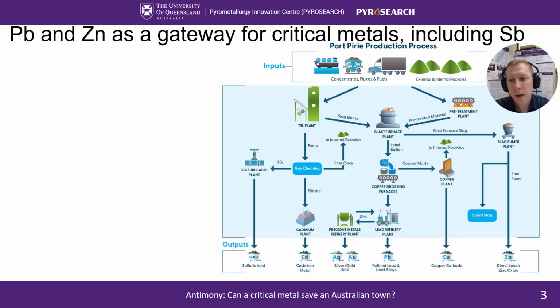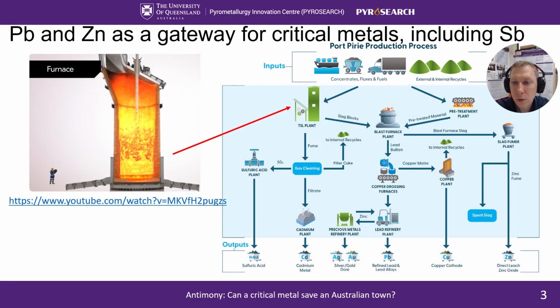This is a simplified flowsheet of the lead and zinc process. The raw feed arrives on ships, trains, and trucks. It consists of concentrates from lead and zinc mines, fluxes and fuels, but also industrial recycled materials, including those from Hobart zinc operations. The inputs go primarily to the top-submerged lance furnace, the TSL plant, where high-temperature oxidation reactions by an air-oxygen mixture remove sulfur as a dioxide and create a molten slag. This process in TSL is highly exothermic and does not require much fuel.